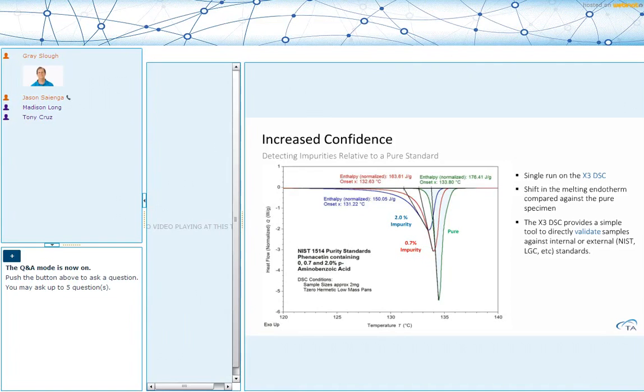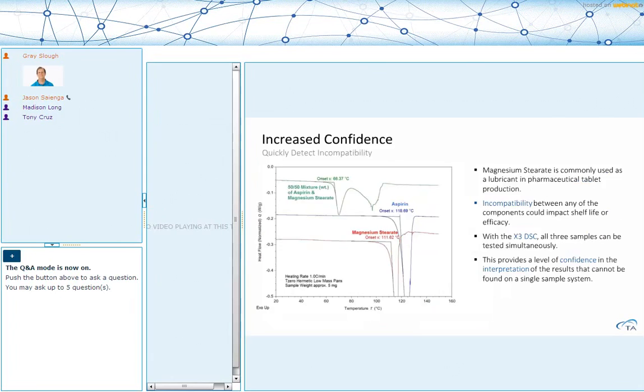And I talked about increased confidence in our results. In this example, it's a single run, and yet we have 3 independent data sets. In this case, it's phenacetin with some impurities, and so we can see that we have 2, let's call them unknown materials, or 2 materials with a level of impurity, compared to a sample that is essentially defined as a pure material, pure phenacetin. So here, in a single experiment, even if you didn't want to go down the quantitative route, you can clearly see that there's differences between these materials. So this is a quick run, and we have a very clear, very easy direct comparison of 3 materials that maybe we know, maybe we don't know, but it adds that level of increased confidence in our results.